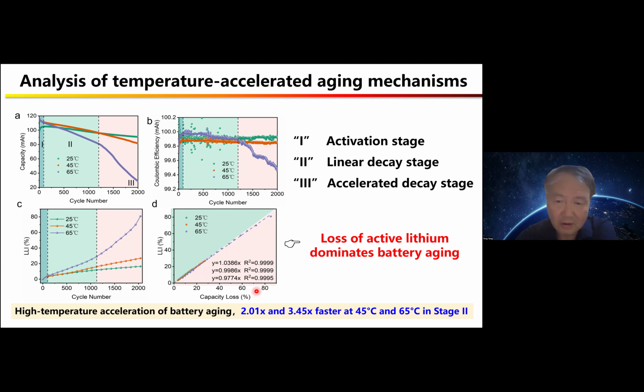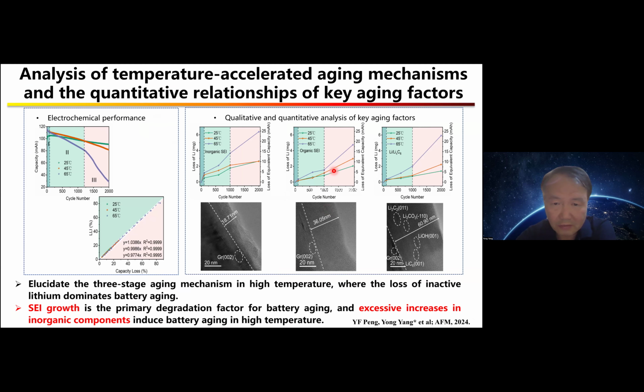We believe that is the loss of lithium inventory in this LFP graphite battery, and that's a major process. That is also interesting - where is the loss of the lithium inventory? If we check the SEI using cryo-TEM, we found that the loss of lithium actually goes to the SEI on the graphite. The more capacity decay, the thicker the SEI.